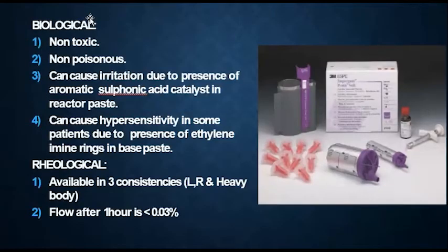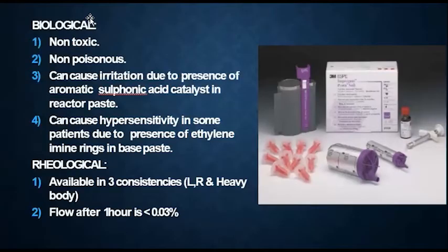So it is non-toxic, non-poisonous. It can cause irritation because of the presence of aromatic sulfonic acid catalyst in the reactor paste, and can cause hypersensitive reaction in some patients because of the ethylene imine rings. So it can cause hypersensitivity and irritation. It's available in three consistencies and flow after 1 hour is less than 0.03%.